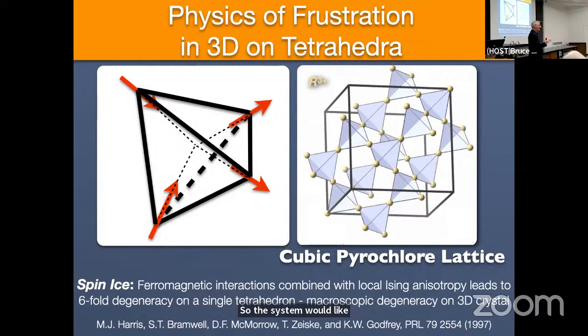If you like, it's almost a ferromagnet, but this single ion anisotropy is precluding the moments from pointing all in the same direction. Okay? So you do get a net magnetization, and it's pointing from left to right over here. So there's a net magnetization going in this direction, but it's not the magnetization of 4 times the individual magnetization of the dipole moments, because they're constrained to not point in the same direction. Okay, so once again, there's a degeneracy for how you arrange the moments which will satisfy the low energy state for one tetrahedron. You need to have 2 spins point into the tetrahedra and 2 spins point out of the tetrahedra. And you could convince yourself pretty quickly that there's 6 ways to do that for any one tetrahedron.